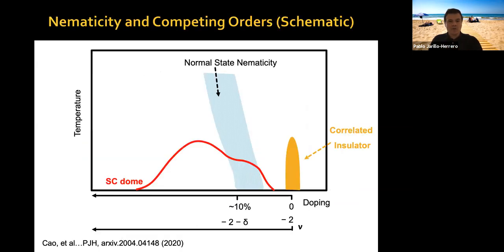So we seem to have, and here's where these two topics that I have spoken about so far come together, in a phase diagram of temperature versus doping in magic angle graphene, we have this correlated insulator state and we have this superconducting dome. Now we have this region of normal state anisotropy, nematicity. This happens in the normal state and it happens over a relatively narrow density range, which at zero intercepts roughly about 10% doping from zero doping. That normal state region seems to deplete Tc in the superconducting dome. So there seems to be competition between whatever is creating this normal state anisotropic state and the superconducting state.